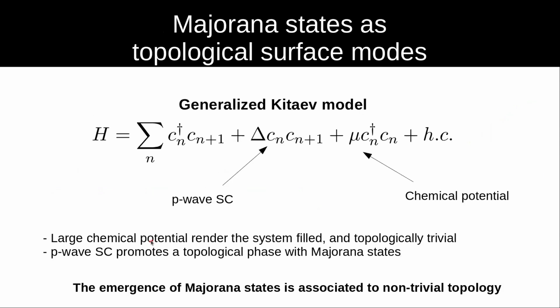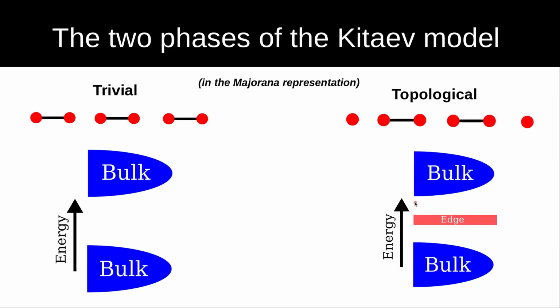And so the idea is that those topological zero modes are actually extremely robust. So now you can start thinking about not taking delta as the same as the hopping, but to have a finite delta and to even have a finite chemical potential. And if you do that, you will see that those zero modes remain there, at least if the chemical potential is not too large. And the reason for that is because those zero modes are topological modes, and they are the topological modes associated to a p-wave superconducting state that, due to its non-trivial topological invariant, has associated Majorana modes.